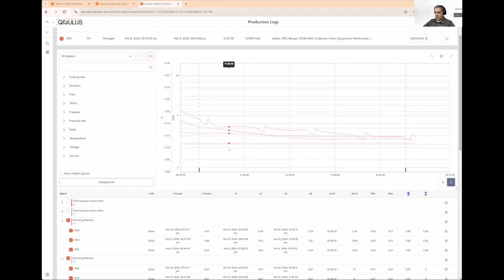So these 3 lines, I could see here that I have in my 7965, 3.82 is my average KN with 0.3 sigma versus 3.5 and 3.52 with a 0.26 or 0.08. So I can see that this job here was 3.5 average with extremely tight KN. It was constant, flat line. This was 3.5 with a little bit of a variation, all the way to 3.76. And this was 3.82 with a plus or minus 30. So it went up to 4.1, 4 point something with a max of 4.7 actually.